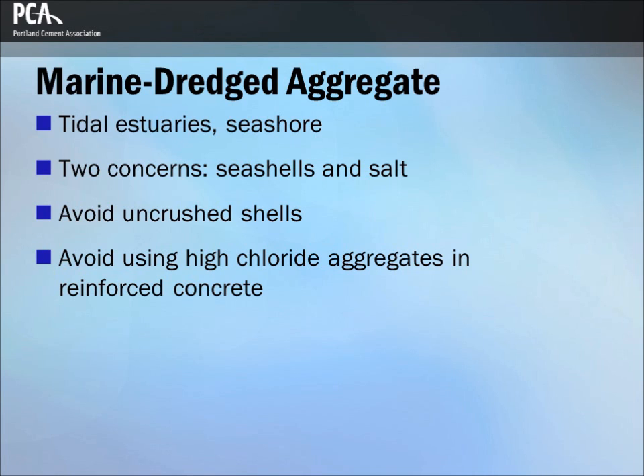Marine dredged aggregate from tidal estuaries and sand and gravel from the seashore may be used with caution in concrete applications when other aggregate sources are not available. There are two primary concerns with aggregates obtained from seabeds: first, seashells, and second, salt. Aggregate containing complete shells should be avoided as their presence may result in voids in the concrete and may lower the compressive strength. Marine dredged aggregates often contain salt, namely chlorides, from the seawater. The highest salt content occurs in sands located just above the high tide level. Generally, marine aggregates containing large amounts of chloride should not be used in reinforced concrete.